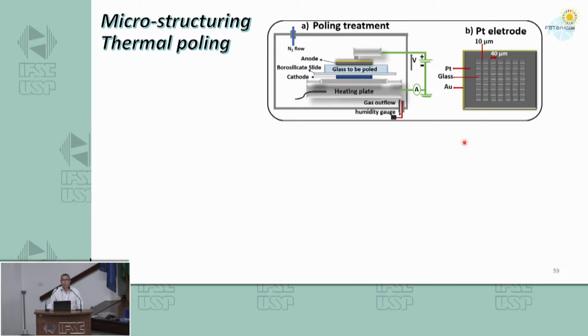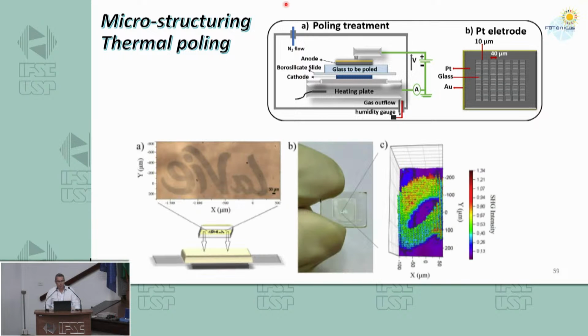This is poling. It's a thermal poling. Thermal poling, you take a glass, you apply a difference of voltage on the surface. You take an electrode, and in this case, it's an electrode like this one. You can imprint this motif on the surface of the glass, okay? So in this case here, our collaborators did the electrode. We imprint it into the glass, and then this is an image of the